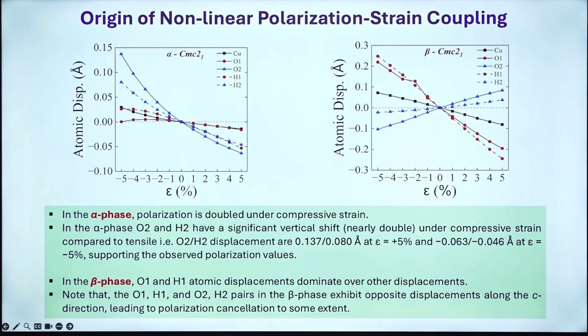In the beta phase, the oxygen 1 and hydrogen 1 atomic displacements dominate over the others. Note that the oxygen 1 hydrogen 1 and oxygen 2 hydrogen 2 pairs in the beta phase exhibit opposite displacement. It is not necessary that all atoms will respond in the same way. One may try to move, and the other will try to compensate. So that is what is happening, leading to a polarization cancellation to some extent. The beta phase is not as good as the alpha phase.